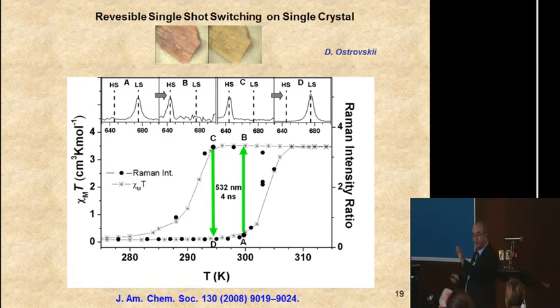Now, could we do the switching in the other side? That means that you write and you erase your information. So then, when we are at the point C here, you see the Raman spectra here, the spectrum is high spin form, without any low spin signature here. When you send your pulse, you go from this spectrum to this one. You see, the high spin disappears completely and low spin appears.